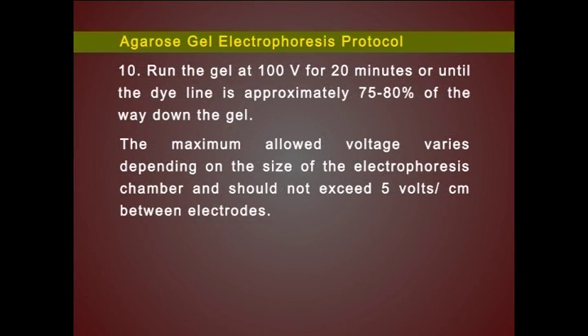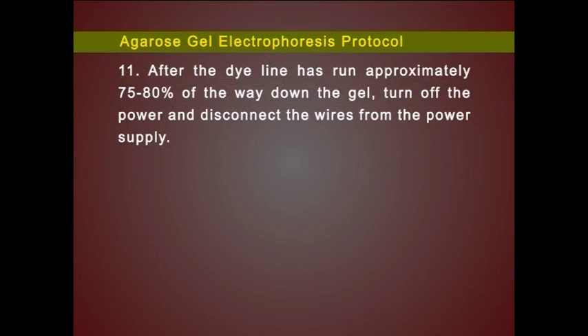Run the gel at 100 volts for 20 minutes or until the dye line is approximately 75 to 80% of the way down the gel. The maximum allowed voltage varies depending on the size of the electrophoresis chamber and should not exceed 5 volts per centimeter between electrodes. After the dye line has run approximately 75 to 80% of the way down the gel, turn off the power and disconnect the wires from the power supply.